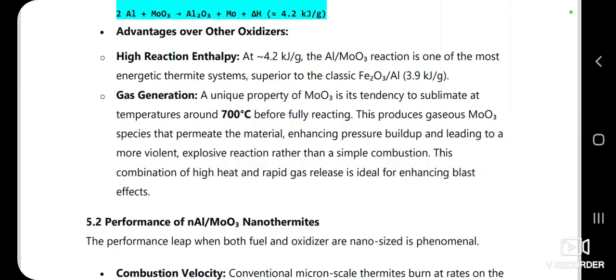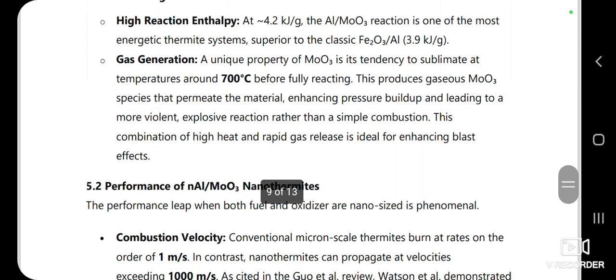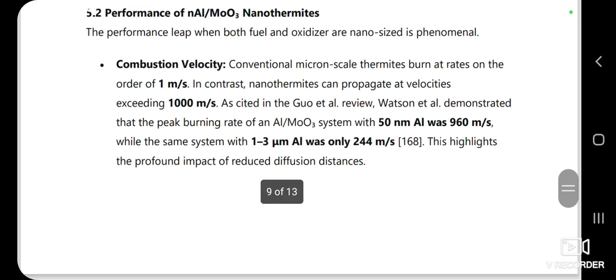This combination of high heat and rapid gas release is ideal for enhancing blast effects. Here's the nano effect in action. Conventional thermites burn at about 1 meter per second, but nanothermites can propagate at over 1000 meters per second. And that's the power of nanoscale intimacy. And this highlights the profound impact of reduced diffusion distances.